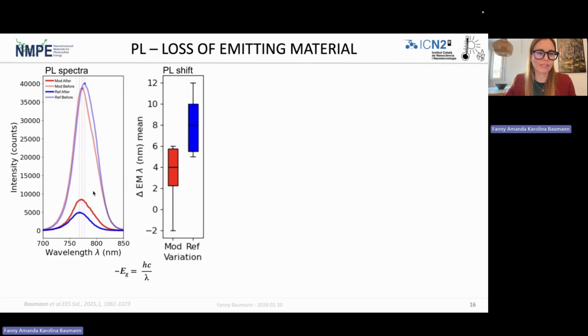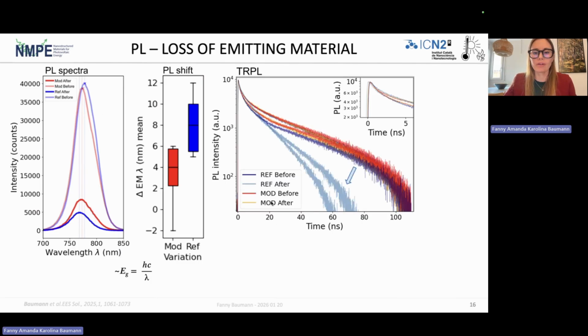Finally, with the photoluminescence, we can see that there's a loss in intensity, a slight blue shift, and we could also see that, especially in the reference cell, there is a loss of photoactive material. So at the longer time scales, there is not as much photoluminescence as in the modification, where we don't see much changes. So this really tells us something about a loss of photoemitting material.